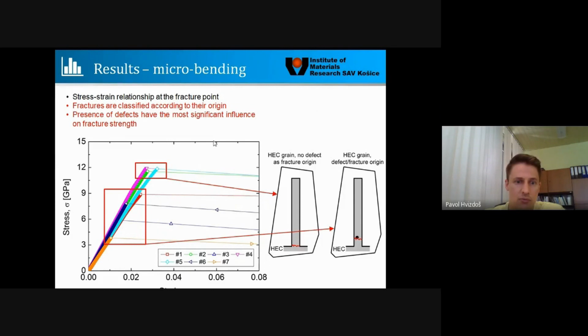Showing the results of microbending, it's slightly different. We found some cases where we could reach stresses of about 12 GPa. It was basically linear. So we didn't see anything interesting, almost linear behavior, and then a fracture. Those curves correspond to those cantilevers which fractured at the fixing, as you can see here, indicated by this red mark.